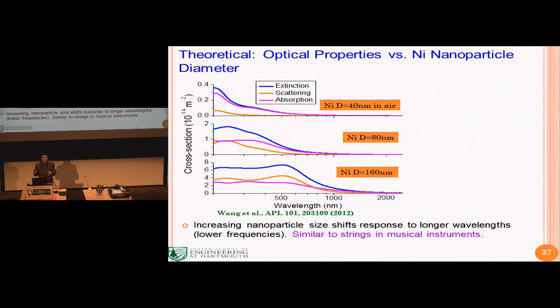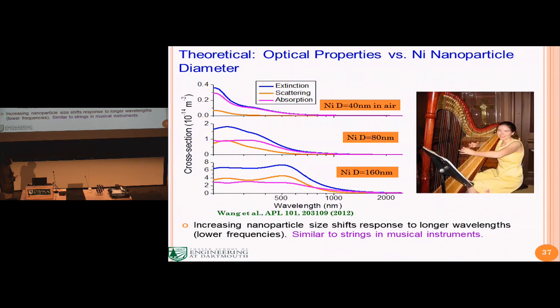Light is an oscillating electromagnetic wave. If that frequency is resonant with the oscillation frequency of the free electron gas in metals, you have strong absorption or scattering inside the material. That intrinsic oscillation frequency depends on the particle size. If you increase the size, it resonates at longer wavelengths or lower frequency. That's exactly the same as musical instruments. You have shorter strings, you play higher notes and higher pitch. So that's an exact analogy there.